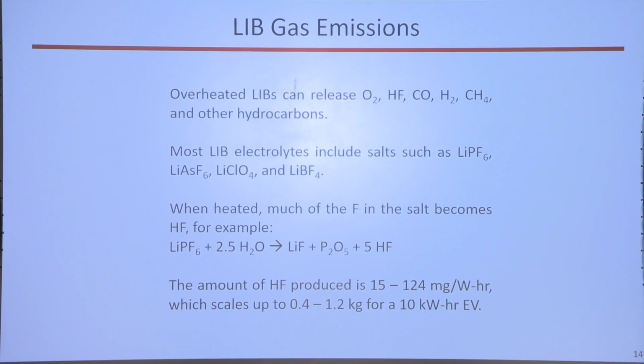But here's our friend now, HF, again released, carbon monoxide, hydrogen. So the last thing you want is a jet of hydrogen, oxygen. Of course these are going to burn, self-ignite. Methane and other hydrocarbons. In addition, there are metals in here too that get released. So the electrolytes include salts, always with lithium, but those include phosphorus, fluorine atoms, chlorine, arsenic is shown there. So depending on what the salt is, there's some nasty metals and compounds that come with that.